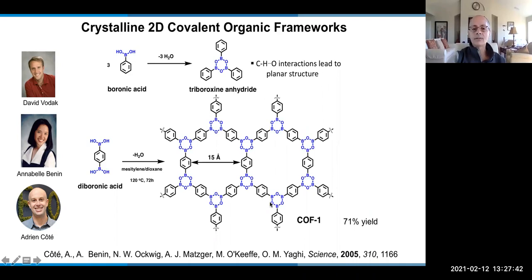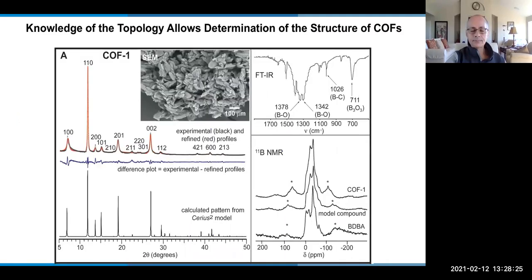And indeed, this was the first COF crystallized in this way, under these conditions, where we use mesitylene and dioxane at 120 degrees C for 72 hours to allow the crystals to anneal and grow so that you have a crystalline material. These conditions are now used routinely to make COFs since we published our work in 2005. You'll see in almost all the COFs that I discuss today that they are based on these conditions with slight modification in some cases, but nevertheless, these turned out to be the magical conditions that allow you to crystallize COFs. Instead of that big amorphous hump, you see now very sharp X-ray powder diffraction lines for COF-1.